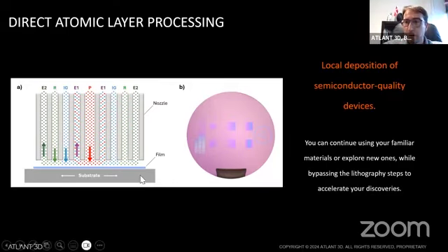by layer materials. And in our case, we made this deposition local, about 300 micrometer local, which enables us essentially to directly write semiconductor devices with standard materials that are available in the semiconductor industry. So you can see the nozzle representation on the left, and you can see on the right some of the processing that we can do. So lines essentially of different thicknesses or gradients.